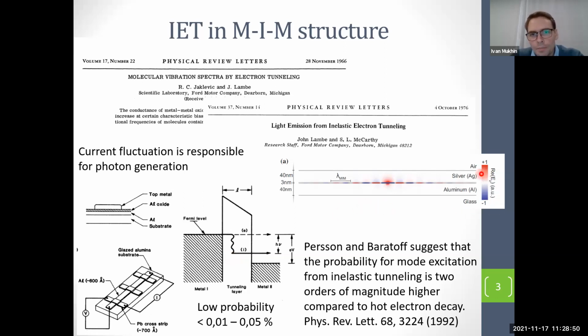As was shown lately, this is the cross section of our crossed stripes. There is one electrode, silver for example, another one aluminum, and a thin aluminum oxide layer between them. And in this modeling result, if we place a point optical dipole in the gap, it's clearly shown that mainly surface plasmon modes localized between the metals can be launched. So it means that if you'd like to observe optical photons in the far field, you need some scattering centers, because SPP waves are non-radiative, and you need to add some roughness or some antennas in the vicinity between the metals on the top layer.